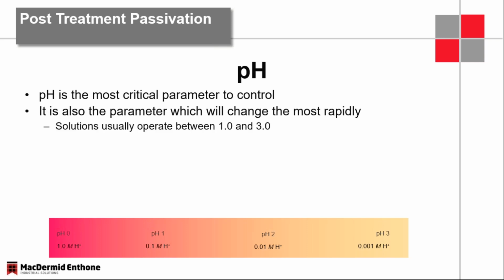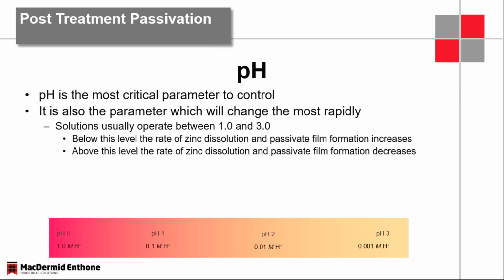Standard between 1 and 3. So your black and your olive drab chromates are usually around 1, maybe a little bit lower. And your trivalent Passivates can be as high as 2.8 or so. So what does that mean? When we were talking about the pH in that diagram before, the lower the pH, the more zinc you're going to dissolve off the part, the faster the film is going to be formed. Not all films should be formed quickly. That's another differentiator between the different Passivates themselves.